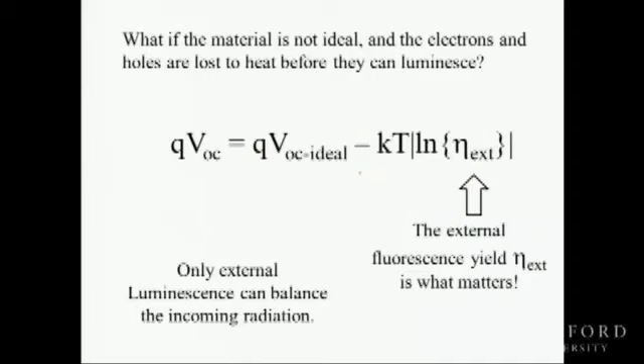And indeed, what Shockley said is this. You have your ideal open circuit voltage, and then you're going to lose voltage according to your external fluorescence. Very counterintuitive, because you'd think all that light coming back at you is wasted energy that you could have used. And nonetheless, it's counterintuitive, but you actually do want to have that light coming back at you, because that allows you to have the highest open circuit voltage. So you want your external efficiency to be 100%. This would be log of 1 is 0. You lose nothing, and you get the maximum ideal voltage that Shockley decreed.